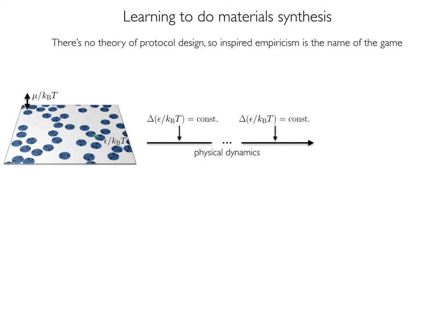We're modeling molecular deposition on a surface, and the control parameters we're interested in are chemical potential and temperature. In the picture shown on the left, the model molecules or disks live on a surface, and they can exchange with a notional bath with a certain chemical potential, and they're held at a particular temperature, which relates to how strongly they bind to each other.